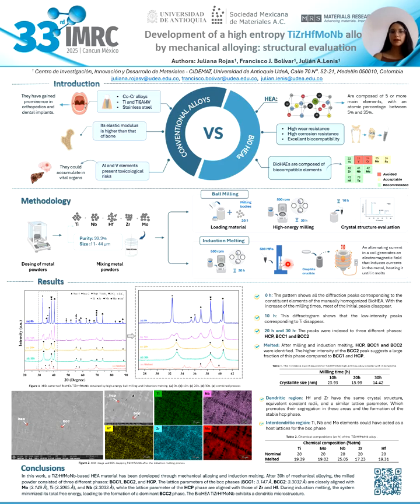These pellets were deposited in a graphite crucible, which is efficiently heated by induction and transfers heat to the metal by conduction. Then the crucible containing the pellet was placed in the furnace coil to begin the induction melting process under vacuum conditions at a temperature of 2071 degrees.